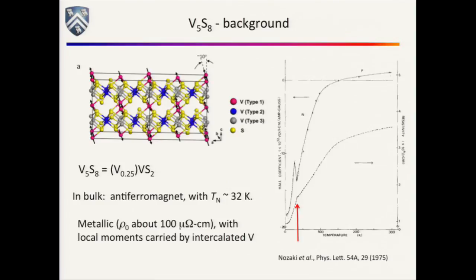It turns out this stuff was already known. The Japanese discovered this in 1975. It's an antiferromagnet. It's a metal. So the idea is that you've got metallic conduction in these layers, and then you've got local moments in the intercalated vanadium layers. It's hard to see the arrows, but the spin structure drawn here is what people infer from making a big crystal and doing neutron scattering. That's what the spin arrangement looks like in the antiferromagnetically ordered state.